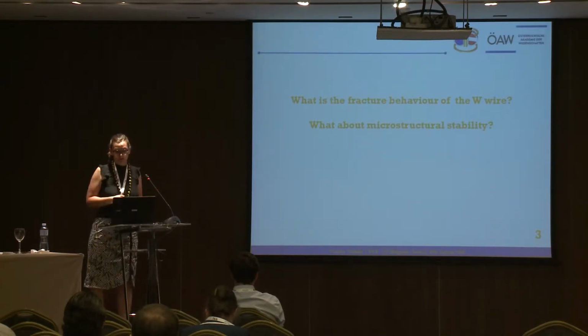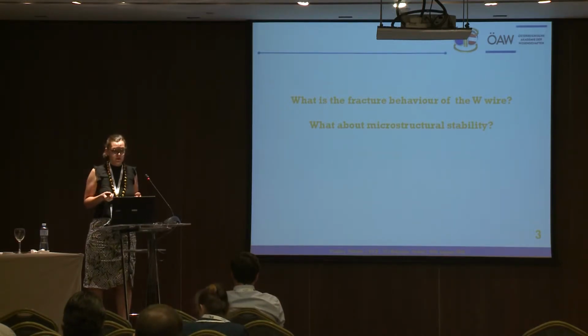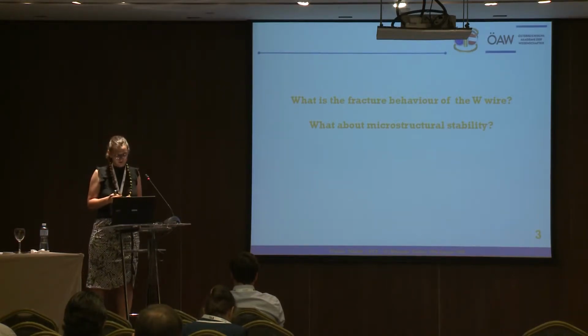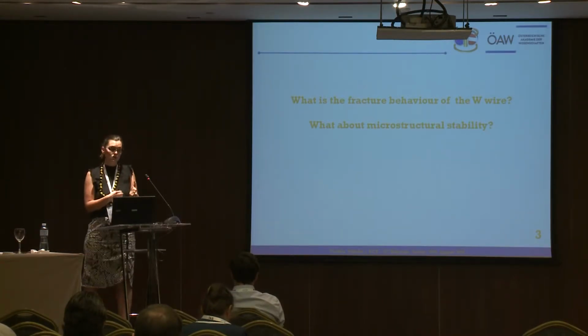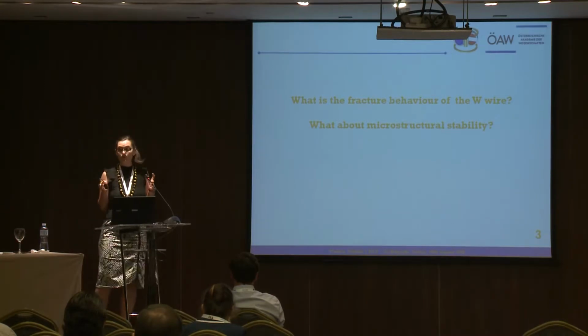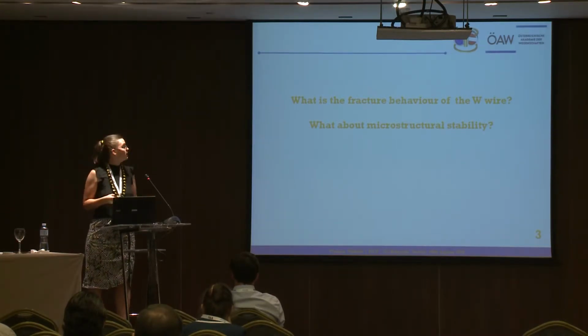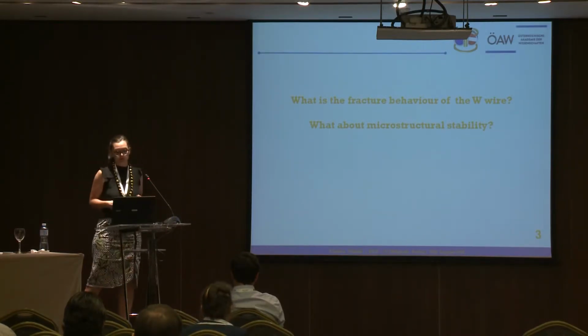As the main reinforcement of such a material, we have the fibers or the wires, and as the whole structural integrity depends on their properties, it is very important to know exactly how they behave with regard to fracture, and microstructural stability is also a very important issue. When thinking of using tungsten in a fusion application, these two things define the temperature limit of use. The DBTT, which unfortunately with tungsten is rather high, defines the lower limit of use, and the recrystallization temperature defines the higher limit. So it is very important to know exactly where these temperatures are and to try to expand this limit if possible.